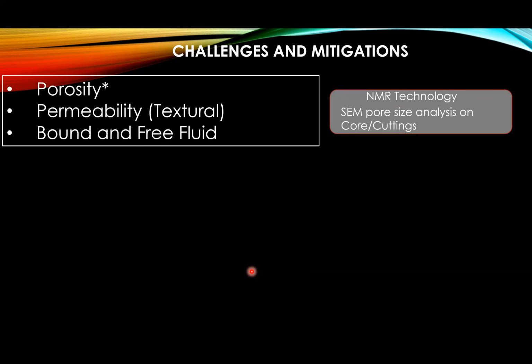So looking at the distribution of the signal, you can derive, or have a fair understanding of, what are my small pores, big pores, or how much of this rock consists of a majority of big pores or a majority of small pores, those kinds of information. And then scanning electron microscope can provide you with a very good idea on grain size distribution as well. And you can actually compare that with the NMR-derived pore size variations also. So that can help you derive porosity, permeability, bound and free fluid. So NMR comes to help you in a big way here, determining all these three critical parameters.